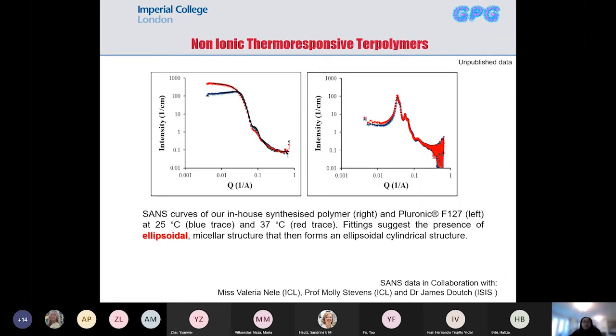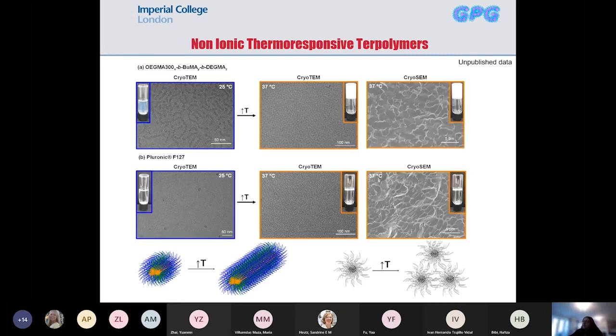Now, what we wanted to investigate is why we have this gelation, and why it is so good that we get it at such low concentrations. So we did neutron scattering experiments at 25 and 37. We can see that our polymer, the one on the left, shows a difference in the scattering at different temperatures. The Pluronic, on the other hand, stays as spheres. The Pluronic forms spherical micelles, and they remain as such, even when they are a gel, they're just more packed in the gel structure. In our case, they are almost spherical. They're actually ellipsoidal micelles, so one dimension is slightly higher. They are ellipsoidal micelles at room temperature, and this structure grows and we form worm-like micelles when we have the gel.